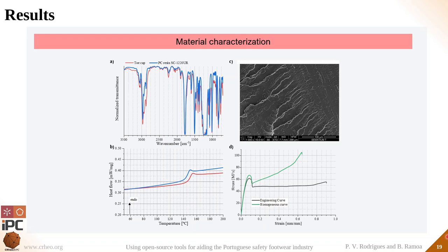Now the only thing left was to identify if this polycarbonate had some type of filler inside, and for this we used scanning electron microscopy to analyze the fractured surface of a polycarbonate sample material. And as you can see, the fractured surface is clean, without any presence of inclusions of fibers or clays or any other foreign material. On the bottom, lastly, we have the tensile curve.